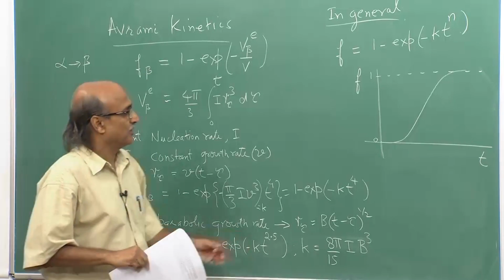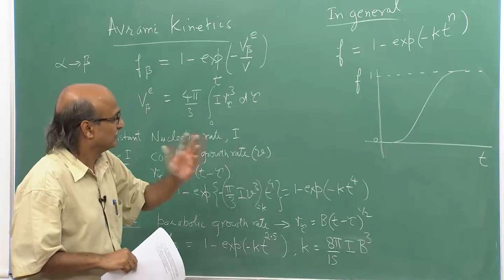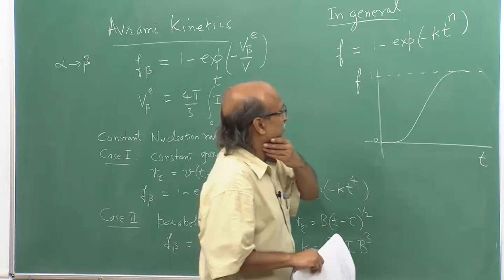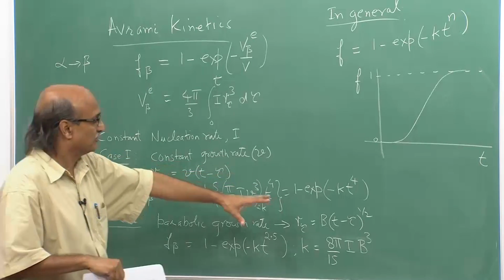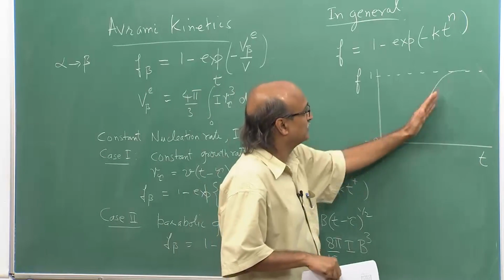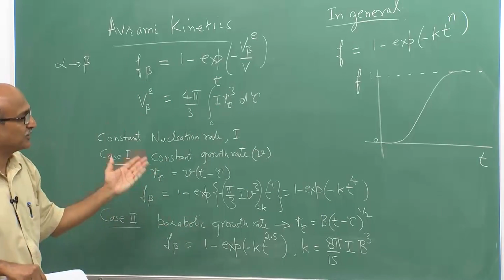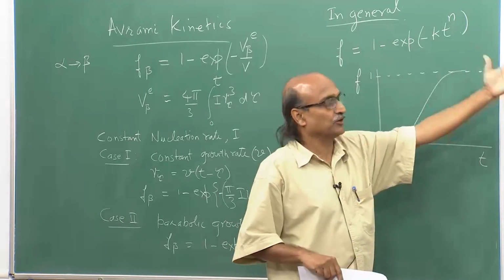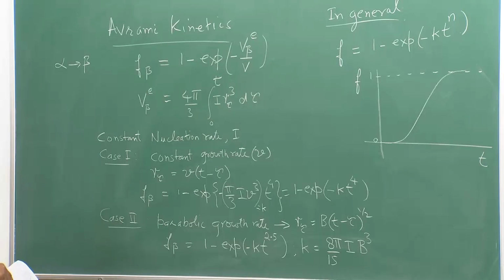In fact, this is the same kind of curve we had got right when we had started discussing the kinetics of phase transformation, and I had shown you a simulation which of course did not assume any of those equations, but the simulation gave me the same kind of sigmoidal curve. And in fact, in that simulation, if you fitted that curve, one would get different values of n depending on what growth model one has taken and what nucleation model one has taken.